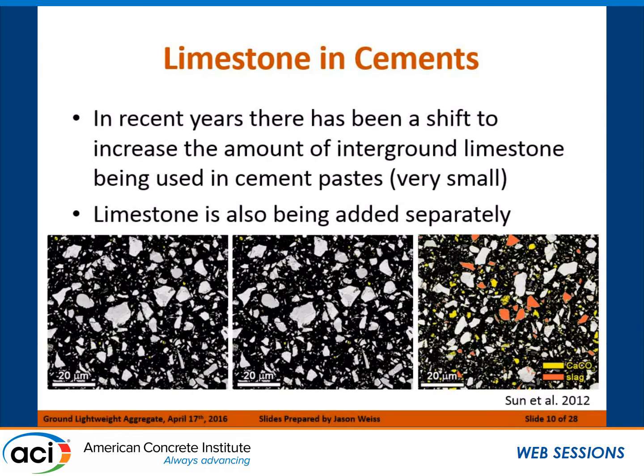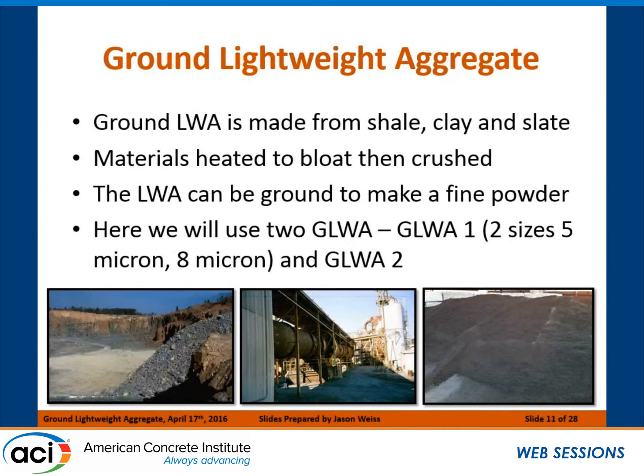The big thing that you need to notice when you look at this is when we're intergrinding the limestone, it's very, very small. All right, so it's a much smaller particle size, and it also impacts some of the overall size of the cement that's inside of the system. And then when we look at a full blended system over here, we can see both the 15% limestone now shown here in yellow, and then 20% slag shown in this beautiful orange color throughout the overall system. So we'll be talking about the effects of intergrinding, but again, we need to remember that when we start intergrinding materials, we're going to have very different size distributions, and the limestone is going to be typically very, very fine.